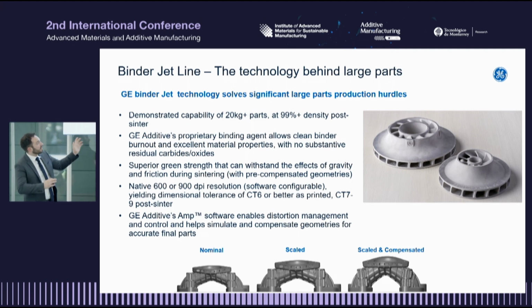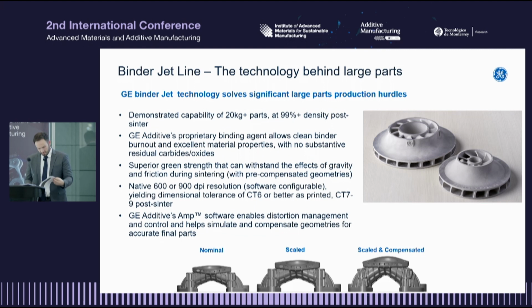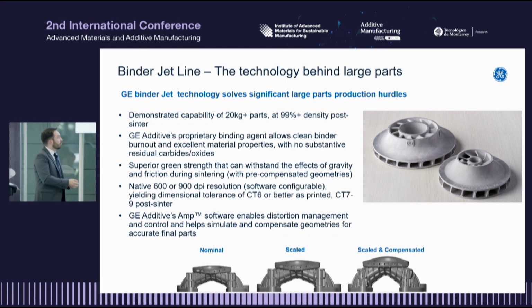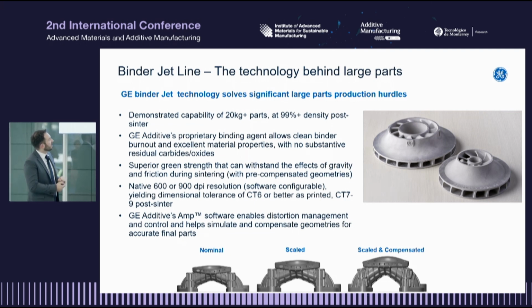But the two that are kind of sizable that we take to trade shows are on the right-hand side of this slide here. The one on the left is 350 millimeters in diameter, and the one on the right is 275. These also went through the AMP software, and you can actually tell if you peek in at the gap in the part on the left. You can see some of the intentional ridge or layer lines that are left over because of the compensation that was applied to the component.